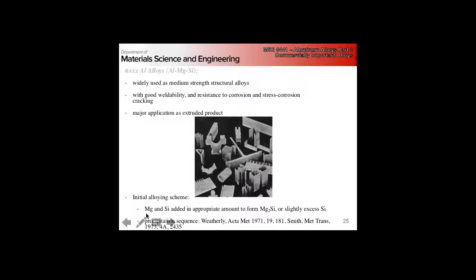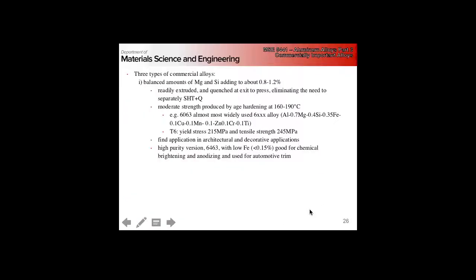The main thing to keep in mind is magnesium and silicon are the main alloying elements, and we want to keep them balanced to form Mg2Si—some alloys have a slight excess of silicon. We have three main types. The first has a balanced, stoichiometric amount of magnesium and silicon, giving a total alloy composition of about 0.8 to 1.2%. This is easily extruded and then immediately quenched.